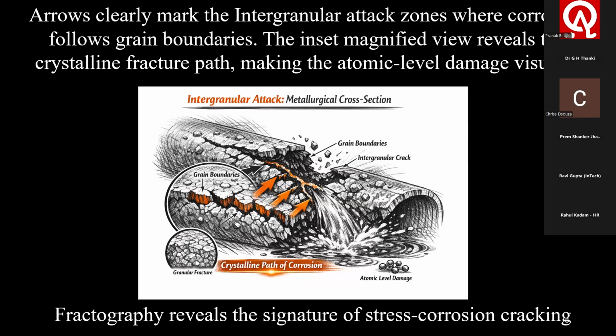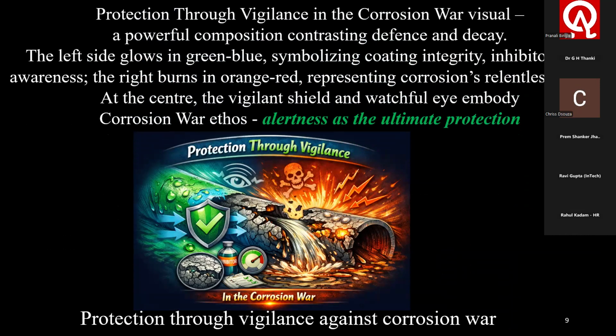This particular slide speaks volumes about how it happens. The fractography reveals the signature of stress corrosion cracking. I'm just touching on one important point, which is going to happen in a big way when sulfur is present in the oil. Now here's the last one. We are showing protection through vigilance in the corrosion war. A powerful composition contrasting defense and decay. The left side glows in green and blue, symbolizing coating, integrity, inhibitors, and awareness. The right burns in orange and red, representing corrosion's relentless assault. At the center, the vigilant shield and watchful eye embody alertness as the ultimate protection.